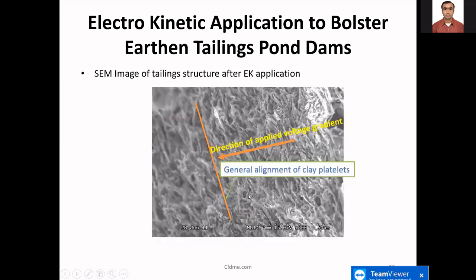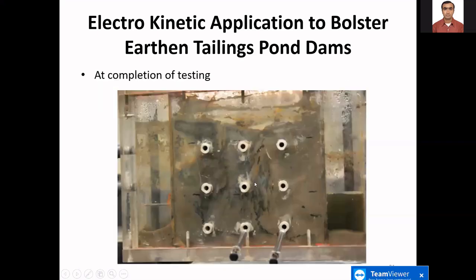But this is what happens to the structure after you've applied the electric field. This orange arrow represents the direction of the applied electrical field. And I tried to draw in here basically the orientation of the clay platelets, which you can see has some variability, of course. I mean, these are minuscule samples, but I was surprised when I did this at how well this lines up, at least overall in a general sense. You've got this subvertical orientation, and you can see that corresponds pretty much with what you see on this plexiglass plate.